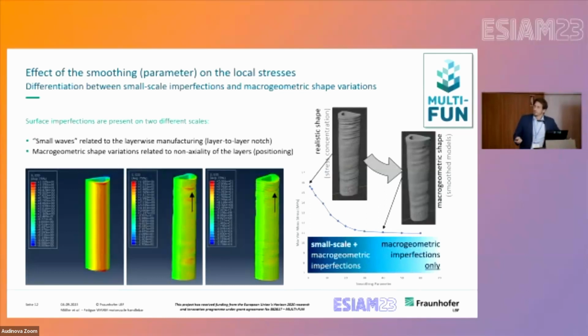And we still see, coming from the ideal model, that with the smooth model we still can find the most likely correct location of the crack. So this is a different specimen compared to the one of the last slide. Ahead of this simulation, there was also a small study giving the relation between a smoothing parameter and the maximum von Mises stress, so that we set afterwards a smoothing value of 40, which is in the area where this von Mises stress converges to a certain limit.